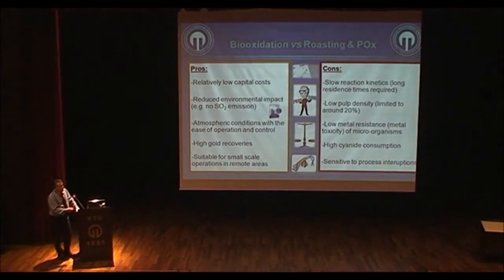Why biooxidation? It is a relatively low capital cost process, and operating costs are also competitive. Reduced environmental impact: there are no SOx or SO2 emissions to the atmosphere, as well as no toxic components like arsenic gases. Atmospheric conditions are used with ease of operation. Its operation is simple, and because it is operated at atmospheric conditions, it's easy to control as well.